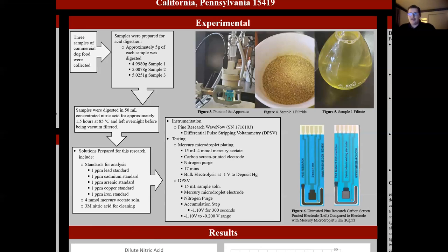As far as testing goes, first each electrode was mercury micro droplet plated. That was done using 15 milliliters of four millimolar mercury acetate, a carbon screen printed electrode, all being purged under nitrogen. This was done by bulk electrolysis at negative one volt for 17 minutes in order to deposit micro droplets of mercury onto the surface of these electrodes. In figure three, you can see the apparatus itself, and in figure six, you can see the screen printed electrodes.